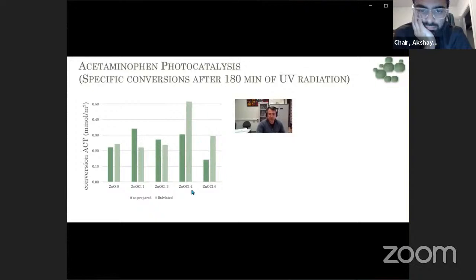It's very interesting because in this case, most of the chloride after lixiviation is in the grain boundaries. Then we have a very big conductivity, and the photocatalysis of acetaminophen is very important when you compare with pure ZnO. And then this shows us that for chloride, it is important to have chloride in the grain boundary to increase the conductivity, but it's not so good to have the chloride on the surface because it poisons the reaction of photocatalysis.